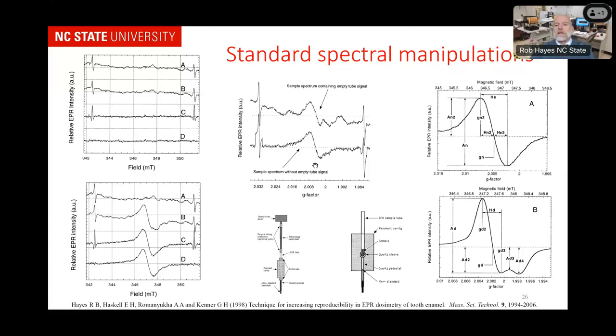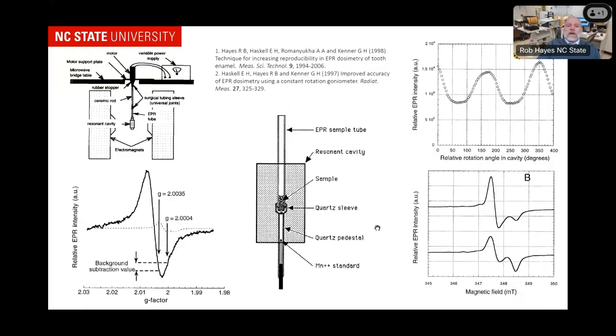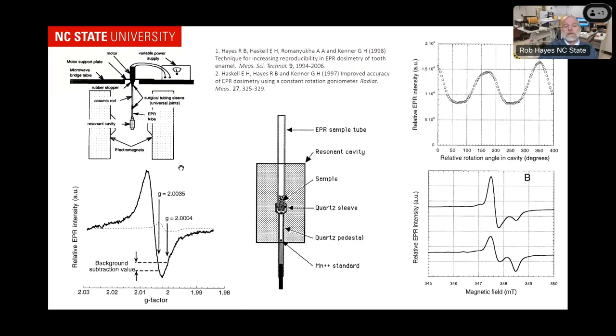This native signal from an unirradiated tooth sample is very useful for epidemiology — with deciduous teeth or similar samples, I can reconstruct that signal. We published the actual native signal standard and the dosimetric signal standard in Measurement Science and Technology. The tooth enamel, being a crystal, is very anisotropic, so if you're using a single grain, the dosimetric signal will be very anisotropic — the amplitudes vary significantly. By using a goniometer or some kind of averaging, I can get much more reproducible samples. These techniques allow you to remove the dosimetric signal, even when it's very small relative to the native signal, requiring spectral manipulation using G-factor standards.